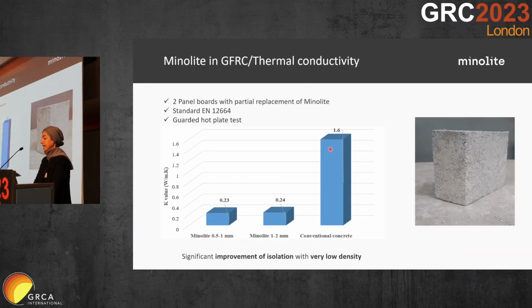We have also done some tests on thermal conductivity. We have produced 2 panel boards, or an external lab has done it, 2 panel boards with partial replacement of Minolite, following standard EN 12664 and the guarded hot plate test. These 2 are where we have used Minolite with different particle sizes. The thermal conductivity is very low compared with conventional concrete, which is 1.6. So thermal conductivity has a significant difference.